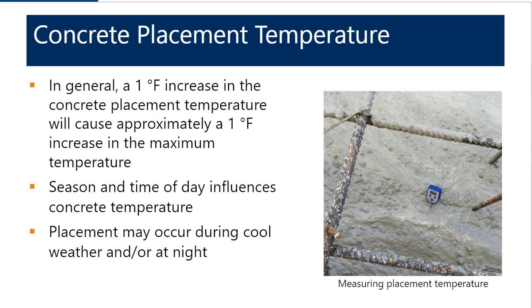So concrete placement temperature is a very significant factor in mass concrete. The general rule of thumb is that a 1 degree increase in the placement temperature is going to cause approximately a 1 degree increase in the maximum temperature. And again, that's a rule of thumb, but it holds true in most cases. And so as a result, the time of day and the season in which you place concrete, because that affects your placement temperature, that ultimately will affect your maximum core temperature for a given mix design and a given element type. And so as a result, one of the easiest ways to reduce your placement temperature is to place concrete at night or at cooler portions of the time of year.